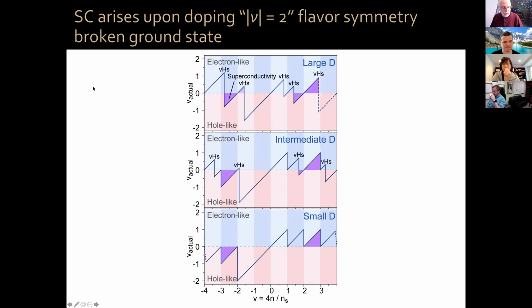Andre-Marie? Yes, thank you for this nice talk. So at the beginning, you mentioned that there was a canonical transformation in the trilayer case that, if I'm not mistaken, led to bilayer plus single layer graphene, right? Yep. So if I go back to the real system, there is no broken top-down symmetry, despite the presence of interactions. Is that right? There is mirror symmetry with respect to the middle layer in twisted ABA stacking trilayer graphene. Yes. Okay, that survives. I mean, the thing is just a canonical basis transformation. Yes. Okay. Thank you very much.